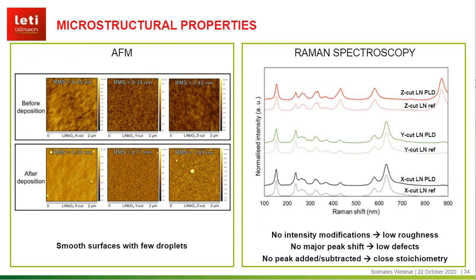Our concerns are a bit more about the roughness and the droplets that could result from the deposition. However, as the AFM images show, we had a low rate of droplets and roughness values close to other classic PVD techniques. And finally, Raman spectroscopy analysis, a comparison between the bulk substrate and the substrate plus the layer by PLD. These analyses confirm all the previous results: the samples have a low roughness, low defects, and a stoichiometry close to ideal.